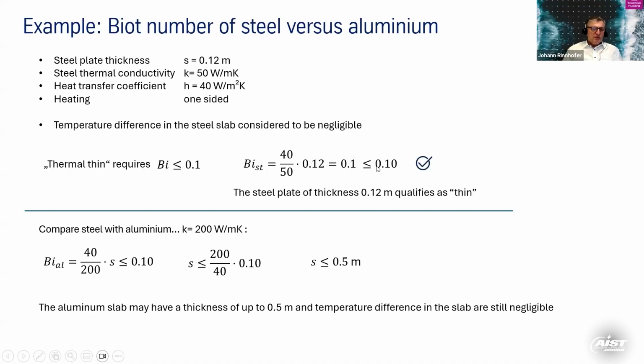And what does it mean for aluminium? We have a different heat conductivity, so 200 compared with 50 for our steel slab. So we have 40 again for the heat transfer coefficient, divided by 200 here. And S, this is what we look for, should be less than 0.1, because this is the magic number for the Biot thick and thin difference. So we say, okay, S can be up to 0.5 meters for an aluminium slab, and it still qualifies as thin. So it might be half a meter thick as compared with steel, which is only 120 mm thick. It still has no significant temperature differences in the slab.